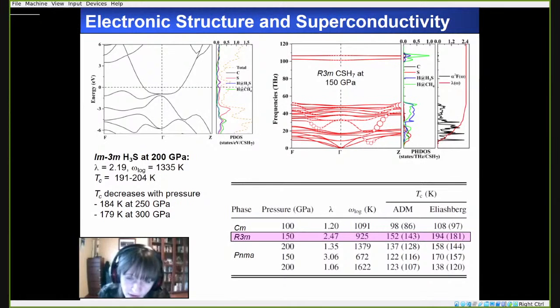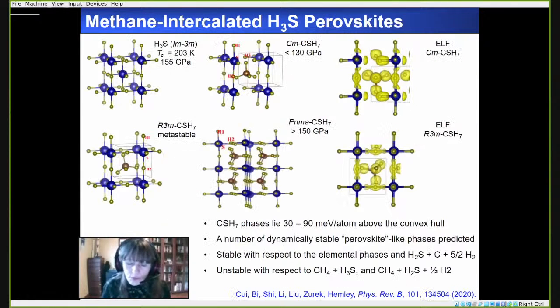Now, these values do not match those that were later measured and published for the carbonaceous sulfur hydride phase that I discussed in the introduction. And therefore, we believe that the phase that was made in experiments differs from the one that we calculated here. Most likely, based upon some recent calculations that have been carried out by us and by other groups, the carbon content of the phases considered in our initial study was too high, and we should be looking at phases with lower carbon content.